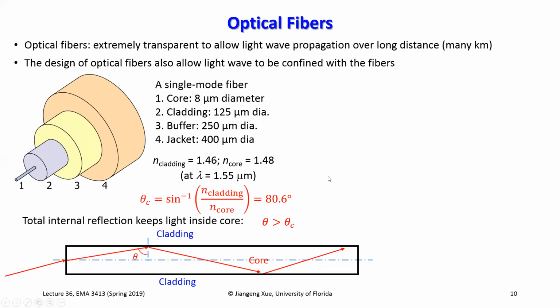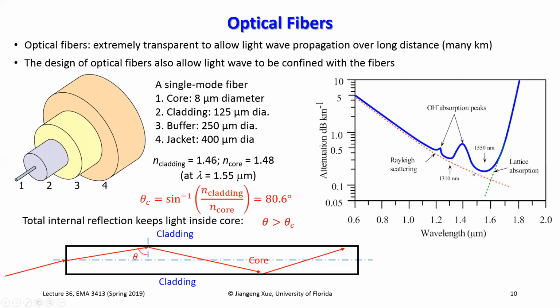On the other hand, the fibers are extremely transparent. You see lattice absorption limiting the transparency at wavelengths greater than 1.5 micron. For wavelengths less than that, we have the Rayleigh scattering behavior. Remember, the Rayleigh scattering is more significant for shorter wavelength light. That's why the sky is blue on a hot, sunny day. So for longer wavelengths, you see this Rayleigh scattering tail. And then we have impurities often existing in the glass, like hydroxyl groups. They will give you certain absorption peaks. So that leaves you a window right at about 1.55 micrometer that gives you the lowest attenuation.